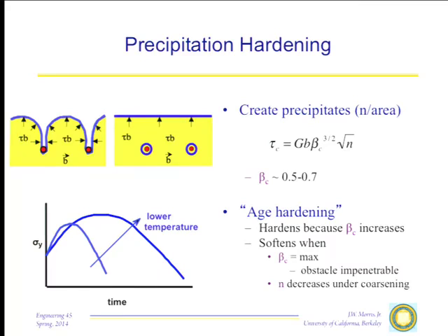So the arms of the dislocations will actually approach one another and come together. The two dislocations on the opposite side of the precipitate, with a little bit of geometric squinting, you can see that they have opposite character, because the dislocation line is running down here and up over there. These two arms of the dislocation, when they meet one another, they will annihilate. So what happens if the precipitates get real strong, and you can observe this in TEM, is that the dislocation will approach the precipitate, bow through, the dislocation arms will annihilate one another, they will move forward, but they leave a loop behind. So there's a little loop of dislocation left behind the particle.